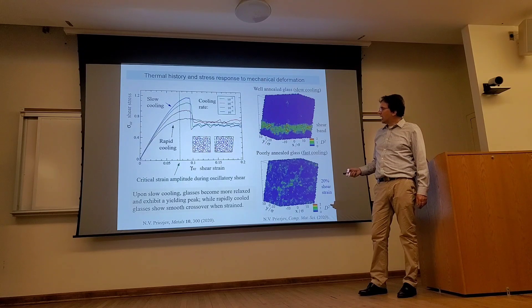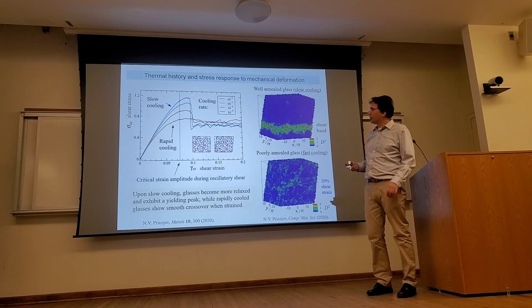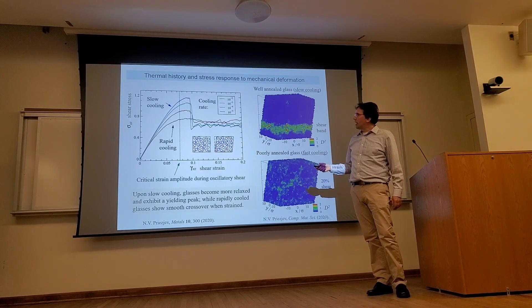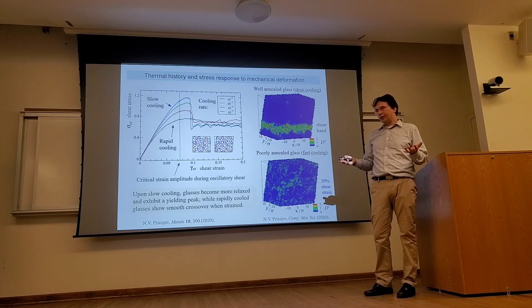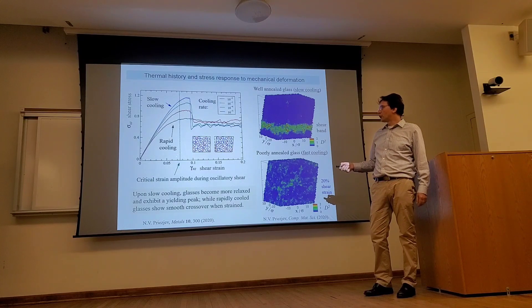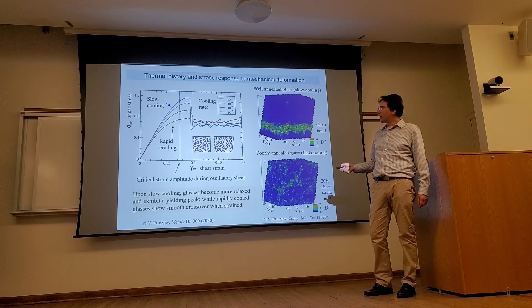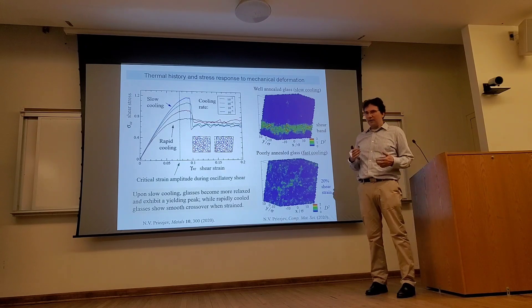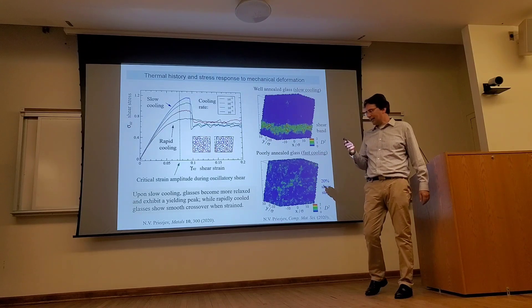It was more recently realized that under periodic shear deformation, the critical strain amplitude is smaller than the location of the yielding peak. In this presentation, we focus on a relatively narrow range of strain amplitudes in the vicinity of the critical value and look at the fatigue and the yielding transition in a model glass.